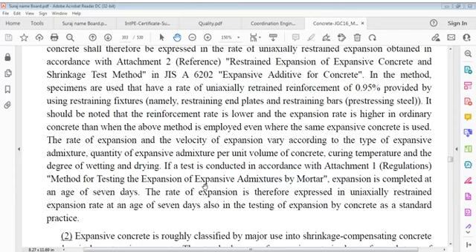Rate of expansion and velocity of expansion vary according to type of expansive admixture, quantity of expansive admixture per unit volume of concrete, curing temperature, and degree of wetting and drying. If a test is conducted in accordance with the attachment method for testing expansion of expansive admixtures by mortar, expansion is completed at an age of 7 days. Rate of expansion is therefore expressed in uniaxially restrained expansion rate at an age of 7 days.